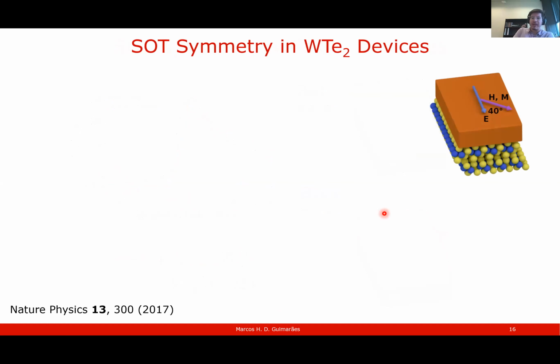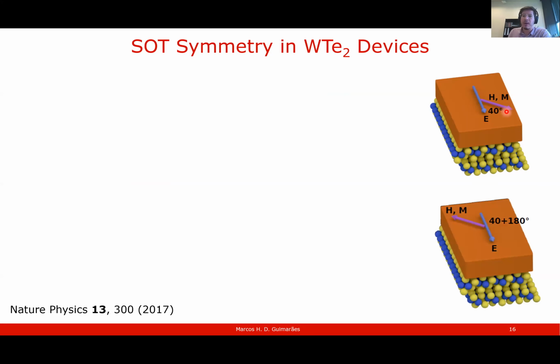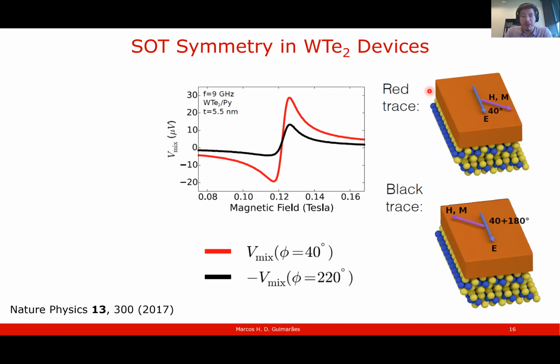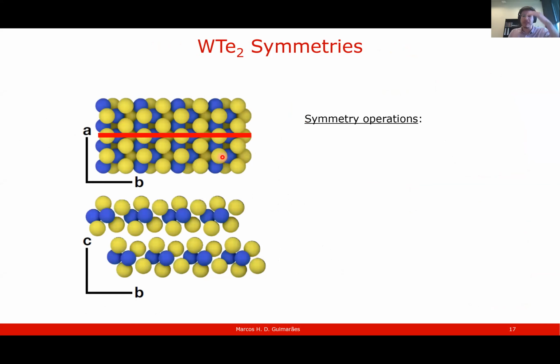But now what happens if you use a material that has a lower symmetry, for example, tungsten ditelluride? So now we have tungsten ditelluride with a ferromagnet on top, and we do the same trick. We apply the magnetic field in a certain direction, measure the STFMR response, reverse the magnetic field, and measure the STFMR response again. And now they look completely different. As you can see here, the black line, which is with the field applied in a certain direction, and the red line, which is the field applied in the opposite direction, are very, very different. It turns out that this can be explained by an even torque, a damping-like or anti-damping torque, which points out of plane and has the form M cross Z. This torque is very special, and it comes directly from the symmetries. You can understand its presence from the symmetries of the tungsten ditelluride.